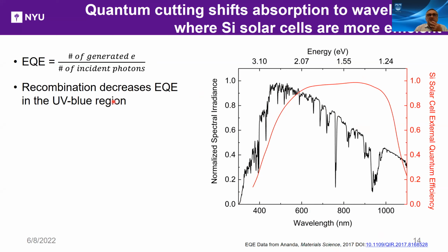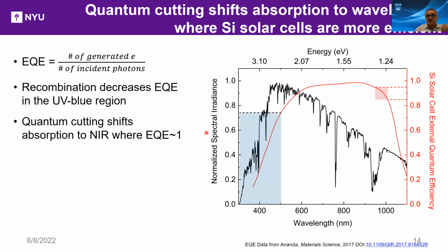And what happens is that in silicon solar cells, because UV gets absorbed near the top of the solar cell, recombination near surfaces decreases the external quantum efficiency in the UV and blue regions. You can see here that below 500, the external quantum efficiency is less than 70%, and for 400, it's even as low as 30 to 40%. On the other hand, near the infrared, the external quantum efficiency is nearing 1.